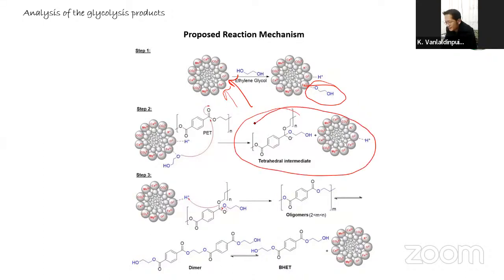That is the second step. And in the third step, the ester bond cleaves in the chain, and that cleavage reduces the PET polyester into lower fractions. As you can see here, the process is reversible, and a chemical equilibrium exists between the oligomers, the dimers, and the monomers. So an optimum condition is needed to get the best possible result.